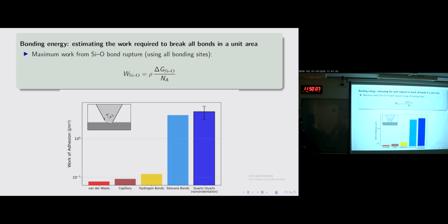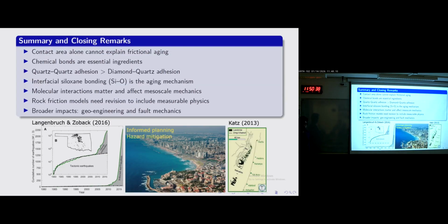This is a log scale, this y-axis. This is the work of adhesion in joules per meter squared. They match up pretty closely. This is the mean plus or minus 1 standard deviation from my sphere-on-flat contacts. If I do the same calculation assuming hydrogen bonds, capillary bridges, or van der Waals interactions, I don't get nearly enough work of adhesion to explain this behavior. Okay, so, close up now.